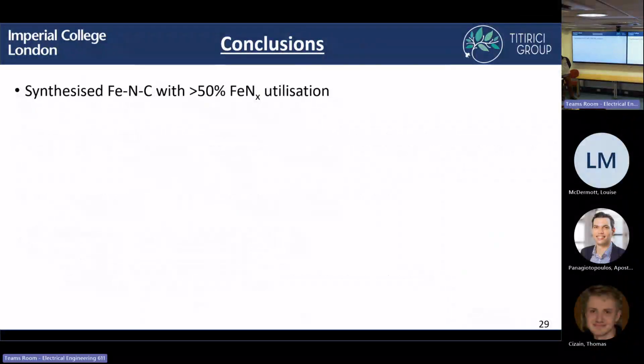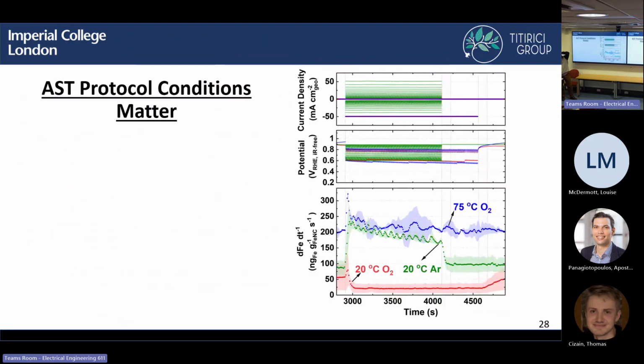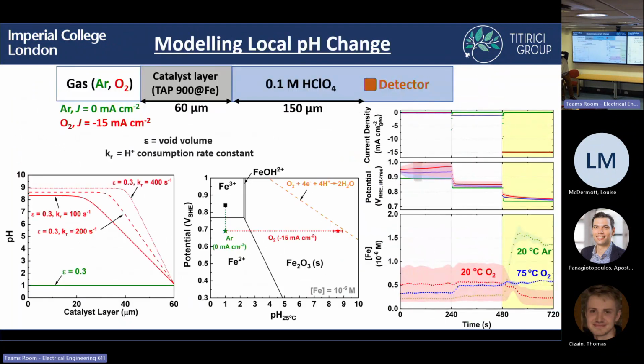With the Pourbaix diagram, you have to consider that this is the potential versus SHE, not versus RHE. So say at the potential of around 0.85, if you convert that with the scales, this is essentially your oxygen reduction to water. So the overpotential would need to be very low. Basically there's no reaction happening here, because this is the equivalent of 1.23 volts versus RHE here. Okay, because this is versus SHE.